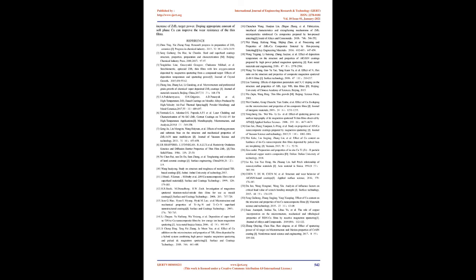This is because the increase of ZrB2 target power increases the content of ZrB2 in the film. Due to the high brittleness of ZrB2, the film is easy to break under the action of friction load, resulting in many fine ZrB2 hard particles. In the process of friction, these small particles that are not discharged in time rub the film back and forth with the friction pair, thus aggravating the wear of the film.